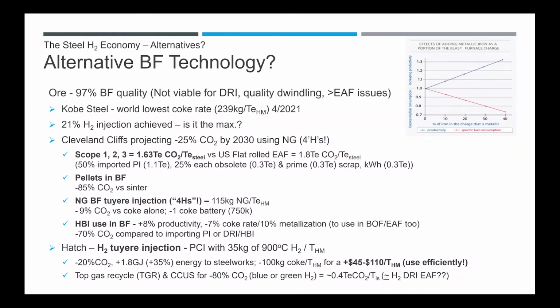So some of the alternatives, 97% of the ore that's taken out of the ground right now is for blast furnace quality only and not viable for DRI and into the EAF. Kobe Steel currently has managed to lower the coke rate to 239 kilograms per ton of hot metal this year in April. And experimentation has been such that 21% hydrogen has been achieved, but question is that really the max as is being specified?